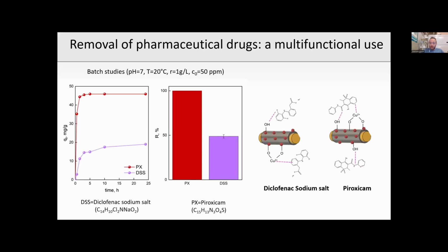But not only anionic dyes, this kind of novel adsorbent is even able to remove other kinds of compounds, such as pharmaceutical compounds. Two pharmaceutical compounds were tested, diclofenac sodium salt and piroxicam. They belong to the non-steroidal anti-inflammatory drugs. And it's possible to observe that the copper modified adsorbent is able to fully remove piroxicam and remove about 50% of the diclofenac sodium salt from the initial water solution. And this difference can be mainly ascribed to the polarity and steric hindrance of the two molecules.